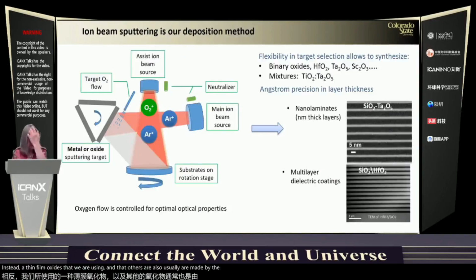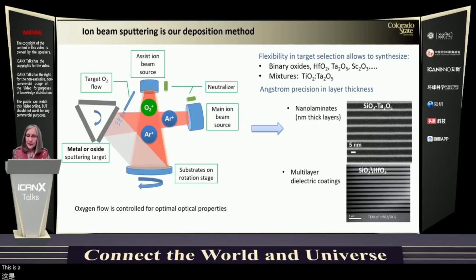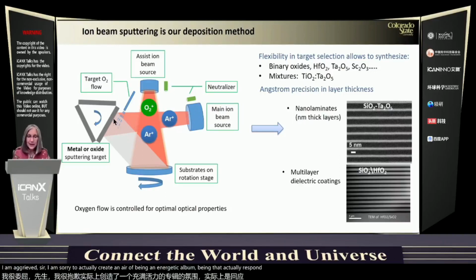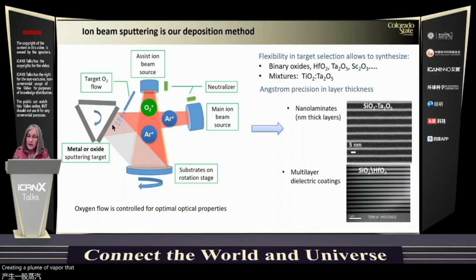Instead, thin film oxides that we are using and that others are also using are made by physical vapor deposition. This is a cartoon of one of the deposition systems that we use to make thin films. This process is termed ion beam sputtering because we use a gridded ion source to create an argon beam, an energetic argon beam that sputters either a metal or an oxide target, creating a plume of vapor that consists of molecules, atoms, and clusters that then deposits on a substrate that is rotating for uniformity purposes.